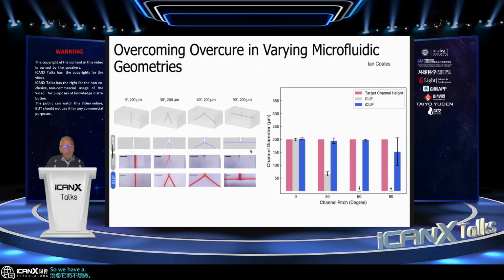So we have a paper pending now. My student Ian Coates has shown that if your channels are vertical, there's no worrying about stray light curing it because the light's just going straight up. And you can make a vertical channel with this traditional process and the injection process. But once you have channels deflecting at an angle, as you start making the follow-on layers, this channel's got resin in it, and the light can stray beyond the layer and cure it.